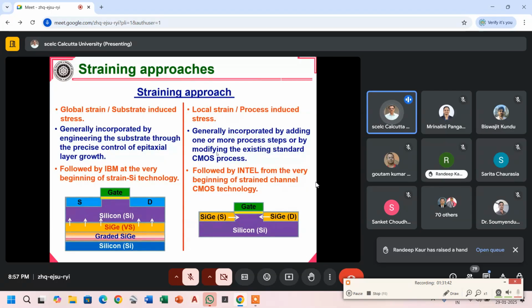What they actually did was take the normal conventional silicon CMOS technology, and in place of the source and drain, they deposited silicon germanium, which has a different lattice constant than silicon. And silicon germanium is an alloy, so its lattice constant is higher than silicon. So when they deposited and annealed it, the silicon germanium started to push the channel region of silicon, which is the technique by which you can incorporate compressive strain. And they did this technology for a different reason.